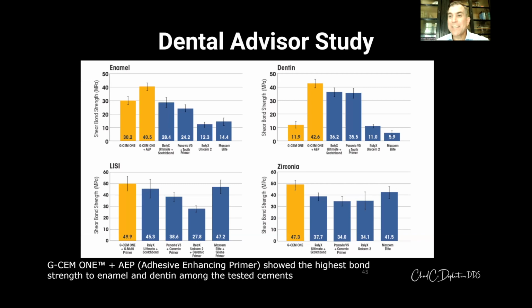So when we look at a Dental Advisor study, this is not an internal study, it's an independent study. You can see that to enamel, the shear bond strength was greatest on the G-CEM ONE, and it performed very well with and without the adhesive enhancing primer. On dentin, you can see that G-CEM ONE plus the adhesive enhancing primer really boosted that bond strength. And then on lithium silicate and zirconia, you can see that the G-CEM ONE performs very well. Now, the adhesive enhancing primer is to be used on the tooth, which we'll talk about in just a minute. And then you'll want to use a primer on the intaglio surface of the restoration.